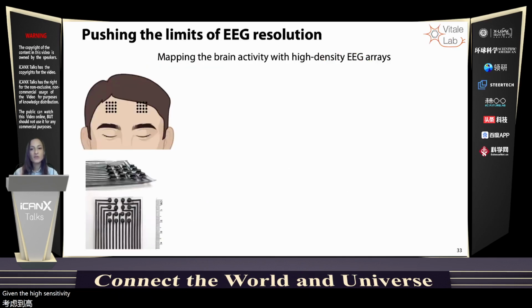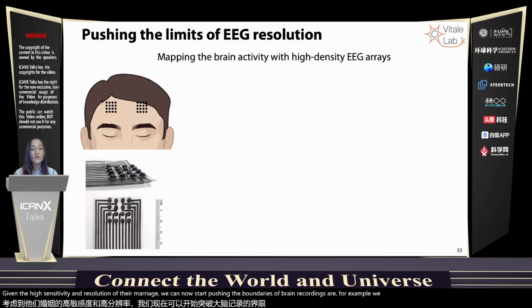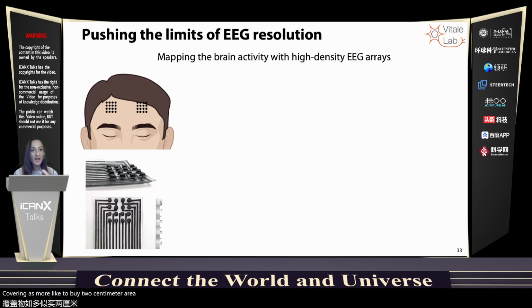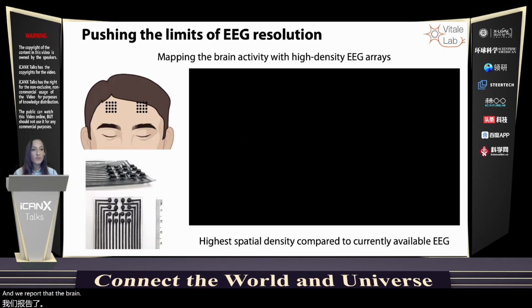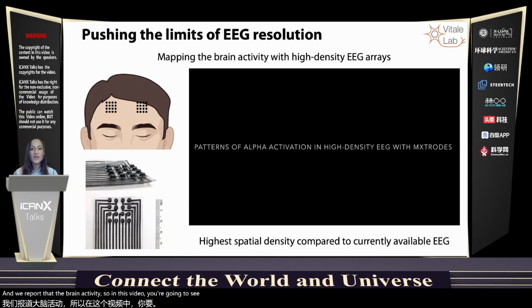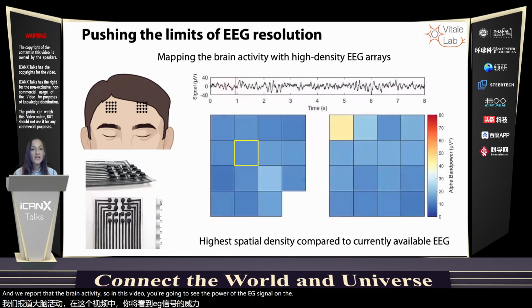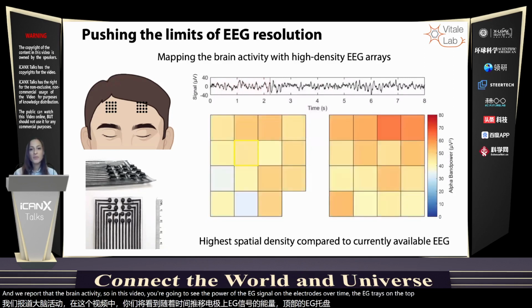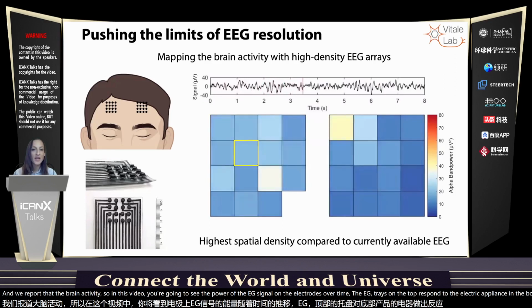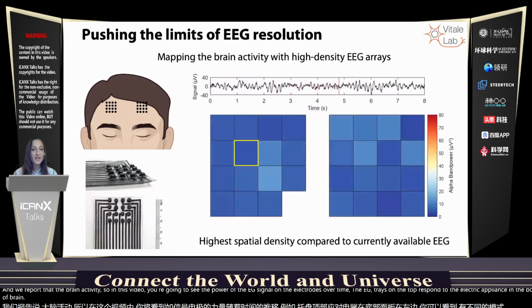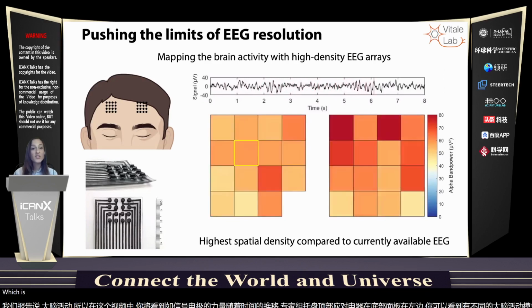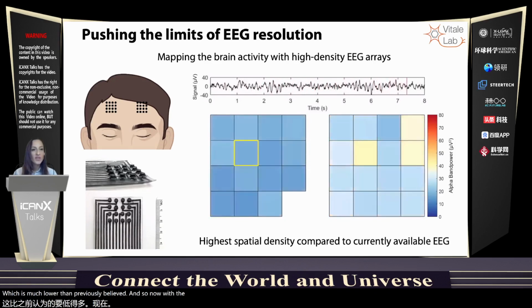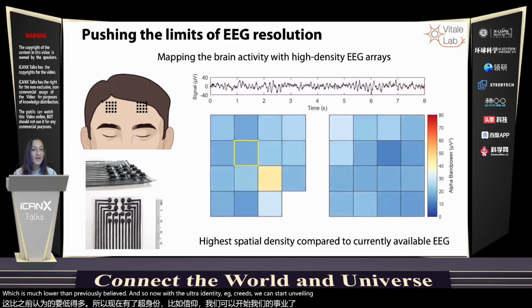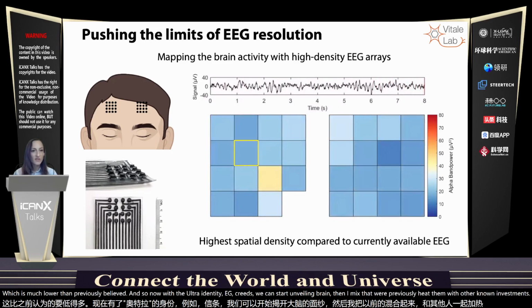Given the high sensitivity and resolution of the MAXtrodes, we can now start pushing the boundaries of brain recordings. For example, we made grids of very high density electrodes covering a small, like 2 by 2 centimeter, area of the forehead. And we recorded the brain activity. So in this video, you're going to see the power of the EEG signal on the electrodes over time. The EEG trace on the top corresponds to the electrode outlined in the bottom panel on the left. As you can see, there are distinct patterns of brain activity that emerge at the centimeter scale, which is much lower than previously believed. And so now with the ultra high density EEG grids, we can start unveiling brain dynamics that were previously hidden with other non-invasive EEG devices.